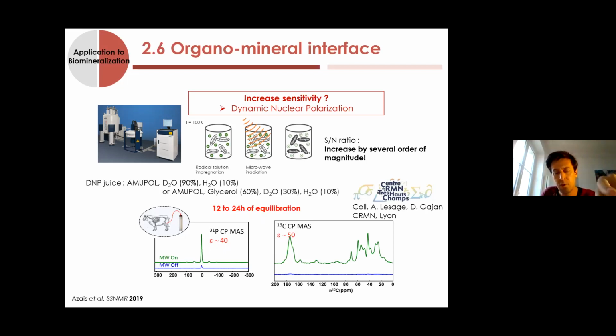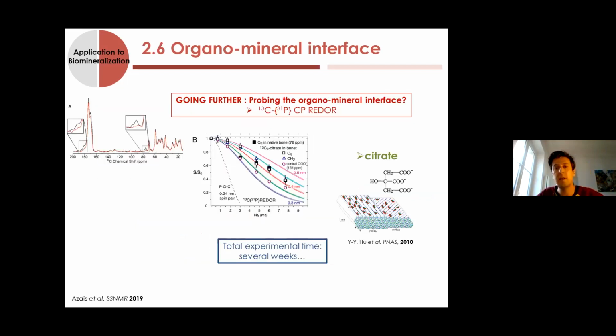Here we'll show an interesting application of that technique. In the case of the organo-mineral interface, if you want to probe it, you need to make correlation experiments between carbon and phosphorus, because carbon is mainly in the organic phase and phosphorus is mainly in the mineral phase.